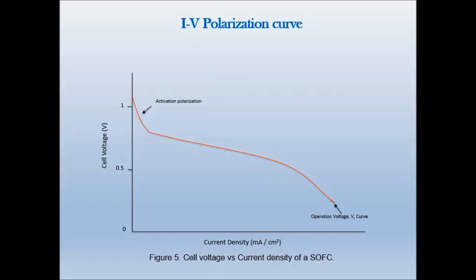At low current density values, the kinetics of the reactions occurring at the electrode surfaces contribute to the so-called activation polarization. At higher current density values, conduction of charge carriers is the limiting process, so that an ohmic polarization is defined, and at relatively high current density values, the concentration polarization is significant. The diffusion of gas species at the electrodes becomes the limiting process. Thus, at any point, the transport and kinetic phenomena contribute to the loss in cell voltage.